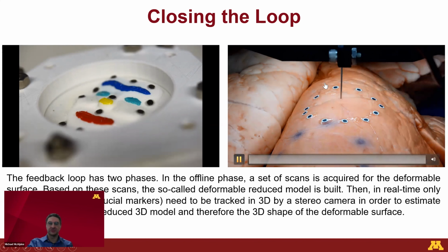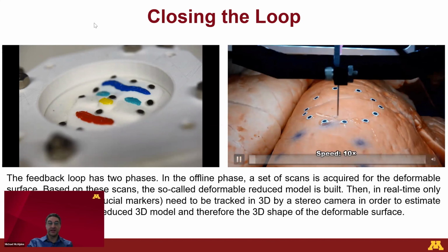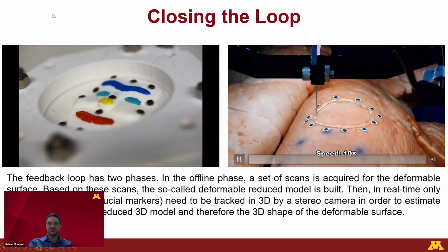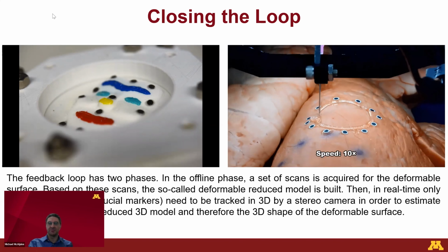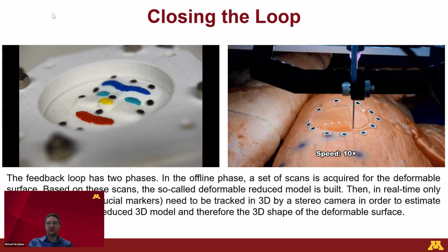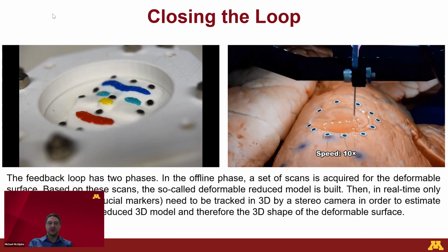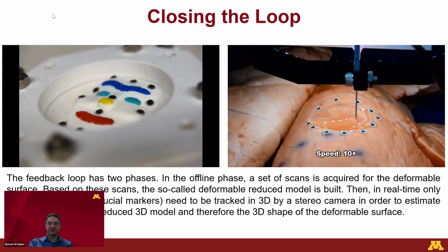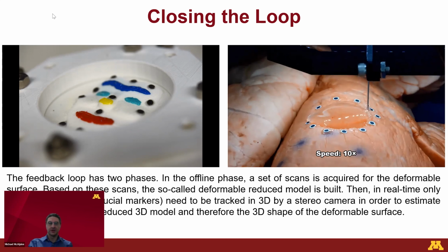And then we took that over to an explanted lung like you see here. So now the lung is breathing and we're watching that motion and printing this sort of strange looking material that you see here. It looks kind of watery, but it's not actually. It's a mix of a polymer and water called a hydrogel. And we're printing that on the surface of the lung tissue, again with the printer watching those motions, those deformations, and able to print this device on the surface of the lung without ever puncturing the lung. You never see the needle puncturing the lung.